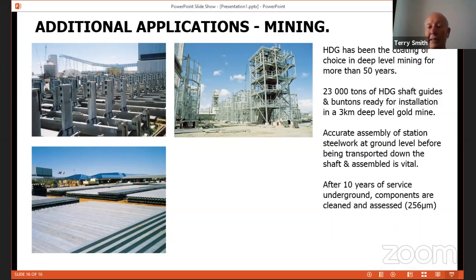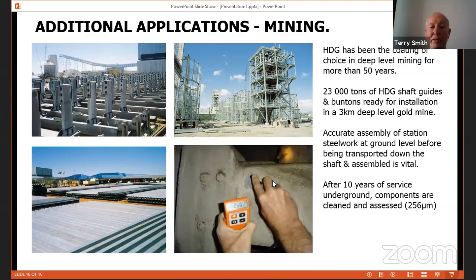After 10 years of service, we often used to get involved underground, assess the components, and you can imagine what this looks like with 10 years of mining. There's a lot of junk on the things. We clean it off and measure the residual coating. And you can see here 256 odd microns.